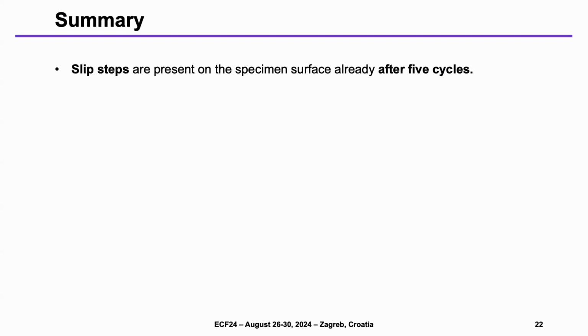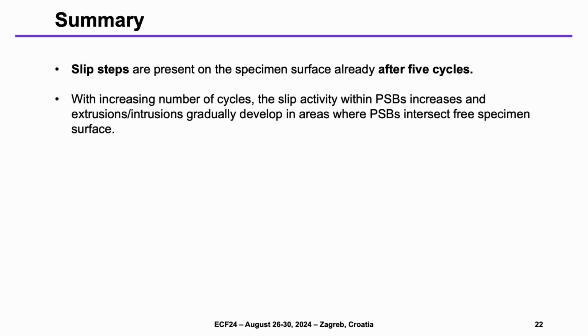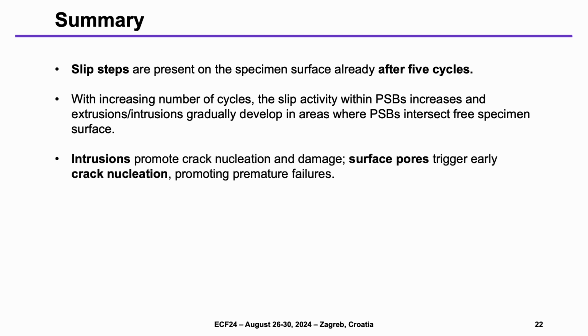So we can say that slip steps are present on the specimen surface just after 5 cycles. Of course, with increasing the number of cycles, the slip activity increases within the bands, and this creates also extrusions and intrusions on the surface of the specimen. The intrusions can promote crack initiation. However, surface pores trigger early crack nucleation.